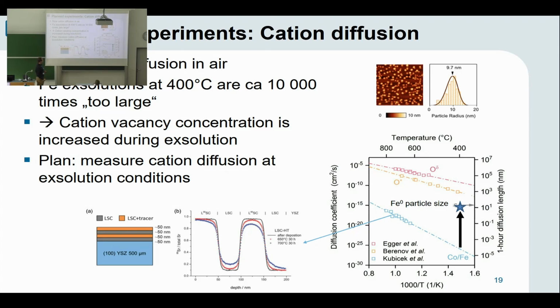However, in reducing conditions where metal iron particles appear on the LSF surface, 10 nanometer size particles are formed at 400 degrees. And those are roughly 10,000 times larger than what we actually expect from the iron diffusion coefficient. And well, we have some ideas why this is the case. It's most likely due to an altered oxygen and also cation defect chemistry in the reducing conditions, and especially during exsolution conditions where a much higher amount of A and B site and oxygen vacancies are present in the material, which ease the motion of the cations. And we want to investigate this by extending these cation tracer diffusion experiments at various partial pressures, and especially also at conditions where metal iron exsolves from the LSF.